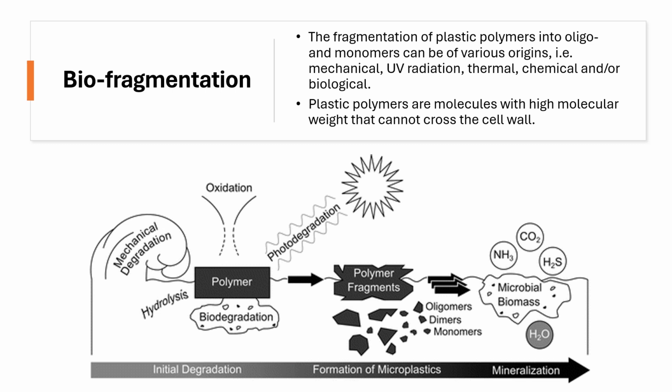The main limit of biofragmentation is the stability of the plastic polymer, which is constituted by a long chain of carbon and hydrogen that contains very balanced charges. To destabilize the local electric charge, bacteria that can break down plastic usually contain an enzyme called oxygenase, which can add oxygen to a long carbon chain.